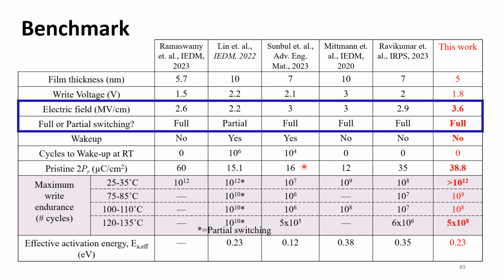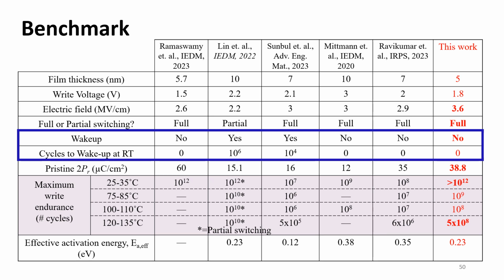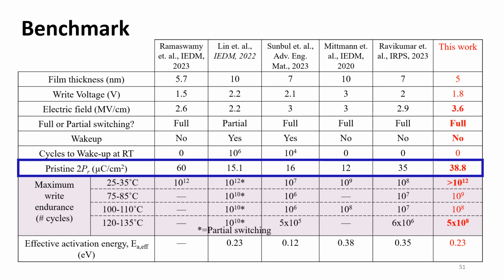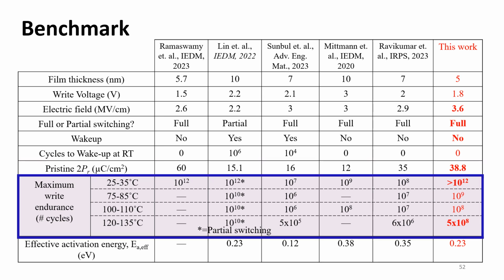We have tried to compare our devices with some of the recently published ferroelectric capacitor results. So here you can see that we have applied sufficiently larger electric field in our measurements just to confirm that we are doing full switching. Although I have discussed extensively about the endurance of the ORL device, it has some good behaviors as well. For example, it doesn't have any wake up, and in pristine state, it is having a pretty decent 2PR value, which is 38.8 microcoulomb per centimeter square. And as I have mentioned, we are getting comparable endurance at room temperature, and we are getting the highest endurance at 125 degrees Celsius for full switching when we are comparing our ORL device with some of the recently published data of ferroelectric capacitors.